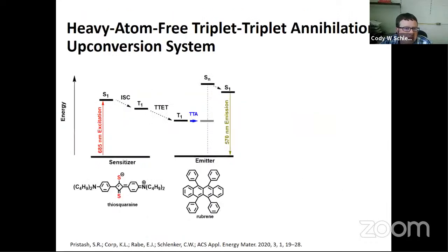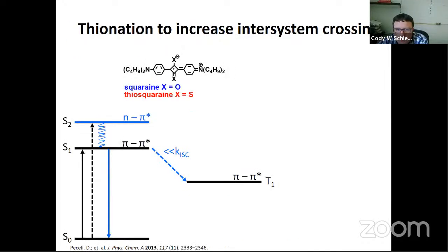All right, so what am I going to tell you about? Well, what we did was we took a dye absorbing molecule, which is a sulfur substituted chromophore here, a thiosquaraine molecule, which essentially takes advantage of something called El-Sayed's rule, which I'll tell you about in a second, and utilizes the change in the orbital character in order to drive intersystem crossing with this molecule, and then you can be off to the races with your triplet annihilation.